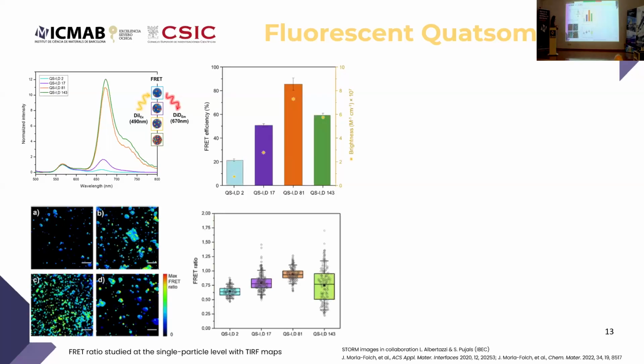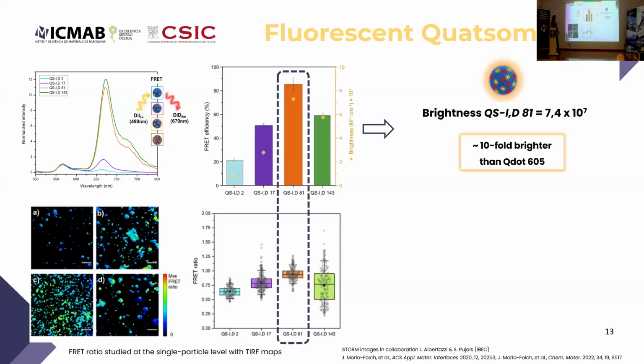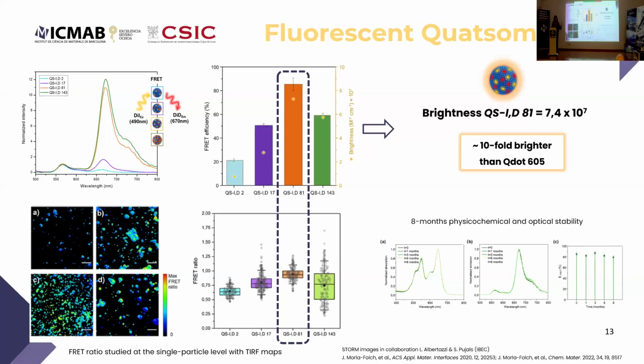When we studied this particle to particle with TIRF maps, it was also very nice to see the heterogeneity that we have. Depending on this loading, this also related to the homogeneity, or heterogeneity in that case, that the different loading gave us. So we obtained this optimal loading with the optimal FRET, and also a very outstanding brightness, reported to be 10-fold brighter than quantum dots, which are a marketed product recognized for being very bright. In addition, together with other data, stability and in vitro biocompatibility, for example, here, 8 months of physicochemical stability in terms of size and shape, but also optical stability: you see that the FRET emission was preserved for at least 8 months.